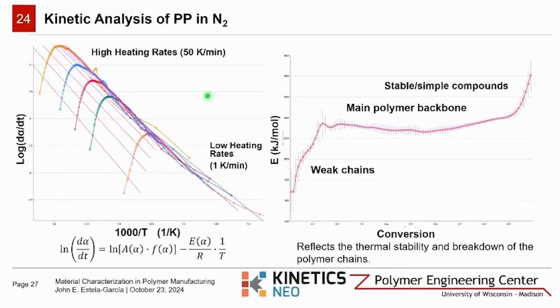So the Friedman analysis of polypropylene degradation in an inert environment reveals insights into the polymer's thermal stability. The Friedman analysis is performed by plotting the natural logarithm of the change in conversion against the inverse temperature over the entire range of conversion. And the slope that we observe here, these are called isoconversional lines. And the slope of these isoconversional lines leads us to calculating activation energy.